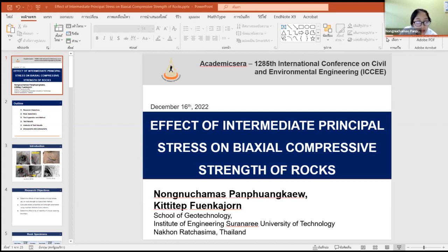The calculated strength and elastic parameters of our tested rocks are shown in this table. Granite shows the highest compressive strength, while gypsum shows the lowest values. When considering the rock strength, it can be seen that the strength initially increased with increasing the intermediate principal stress or with the decreasing load parameter. From these tables, it shows that the maximum strengths are reached at the load parameters of about -0.5. Below load parameters equal -0.5, the major principal stress at failure decreases. This holds true for all tested rocks.